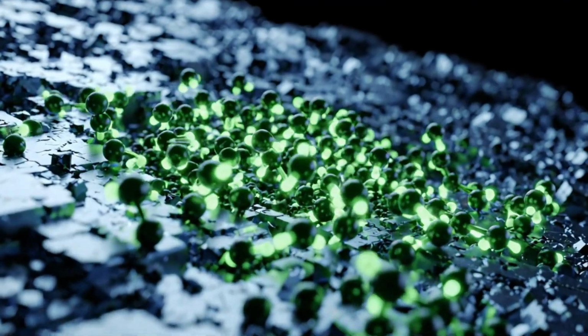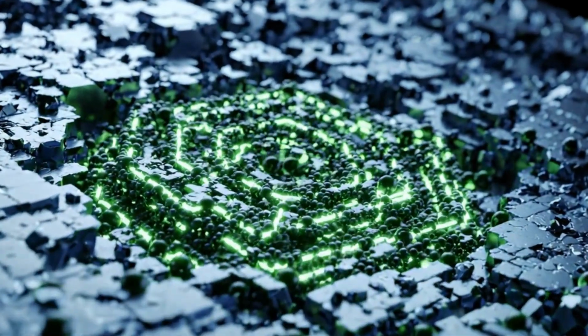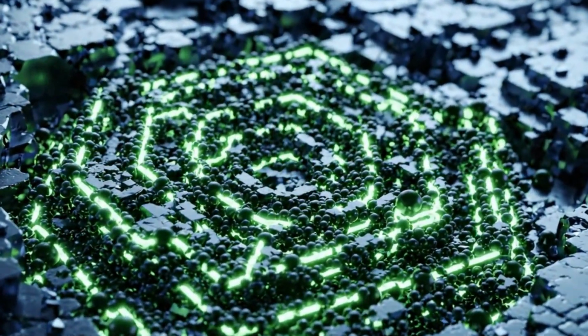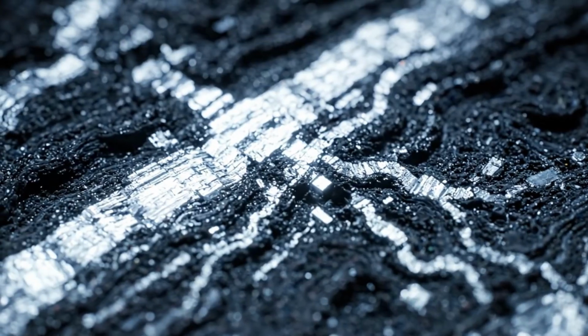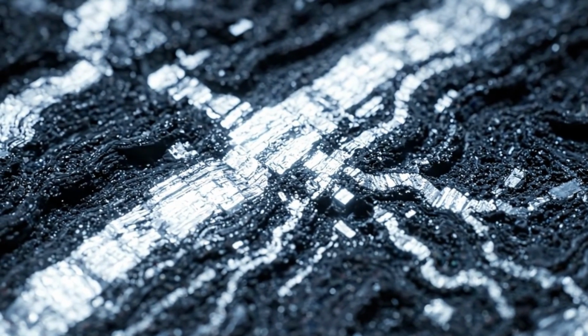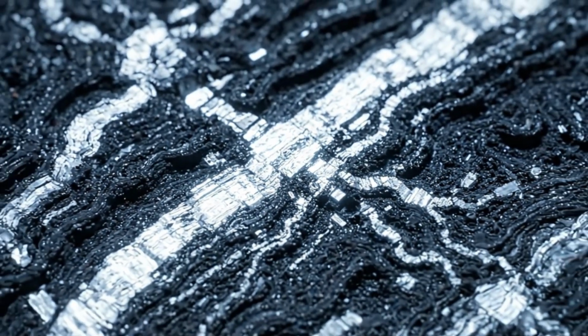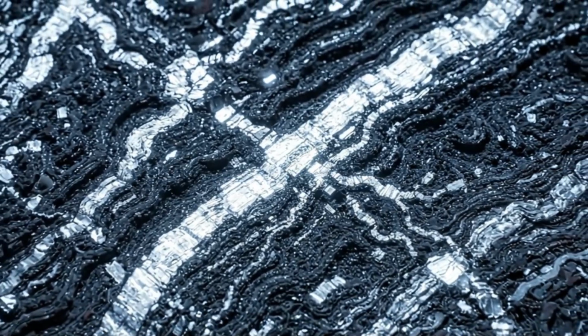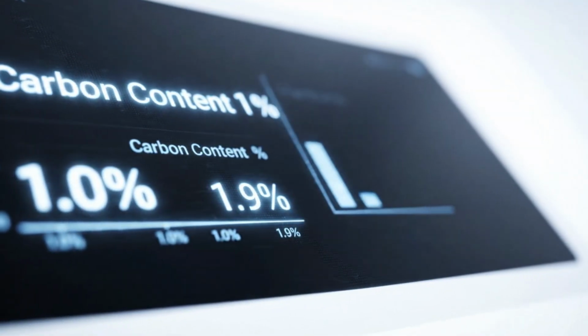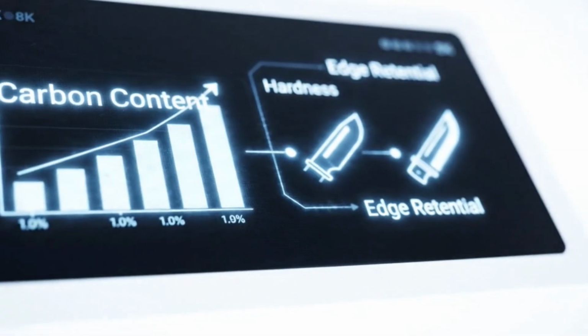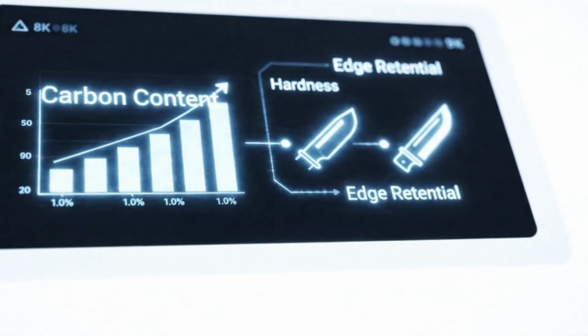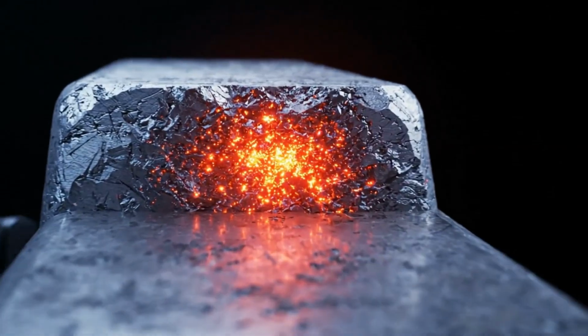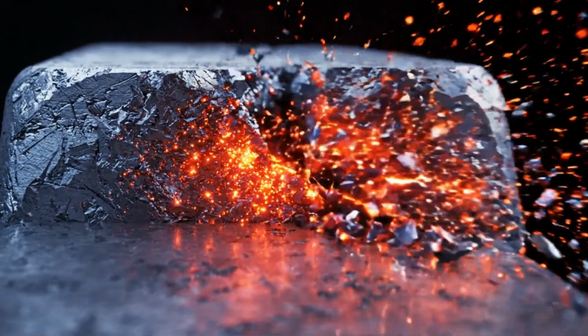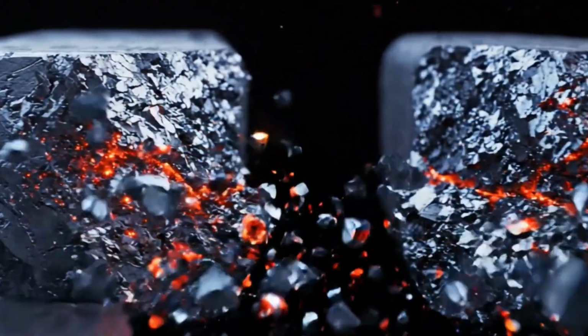The intricate dance of carbon atoms within the iron matrix of Wootz steel, guided by the slow cooling process, created a microstructure that was inherently unique. This microstructure, characterized by bands of cementite, iron carbide, within a softer ferrite matrix, was responsible for both the visible patterns and the exceptional properties of the steel. The high carbon content, typically ranging from 1% to 1.9%, was crucial for achieving the desired hardness and edge retention.